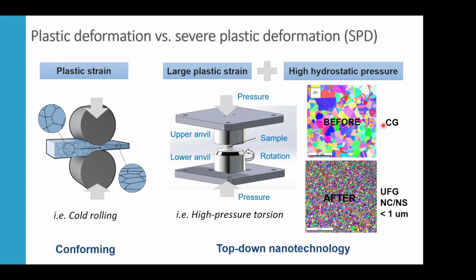So before the processing, we usually have coarse-grained microstructures in metallic materials, and then usually after SPD processes like high pressure torsion, we will break down these grains into much smaller grain distributions, with ultrafine or nanocrystalline size usually well below 1 micron, and that will change depending on the metal alloy or the crystalline material that we process. So it is also considered a top-down nanotechnology synthesis technique.